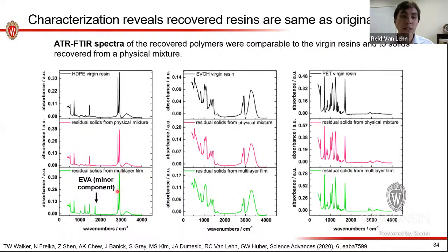You'll notice that these are nearly identical spectra for all three components. The only peak that was different turned out to be because there was another component of the film that Amcor didn't tell us about, which we discovered through our strap process and have now designed in the new iteration of strap to recover as well. So we've got solvents, we've got experimental recoveries. We could reuse these to make films, but is it economically competitive?